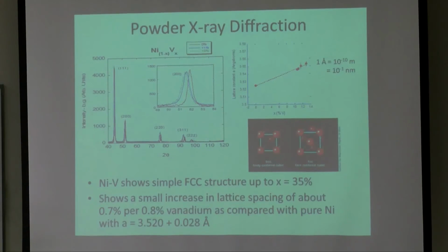So how much vanadium did I put? Very little. This is about maybe 12%, 13% vanadium, so it's not very much. It's still predominantly nickel here. So this gives you an idea of what is in the material. These peaks would give you an idea of the crystal structure.